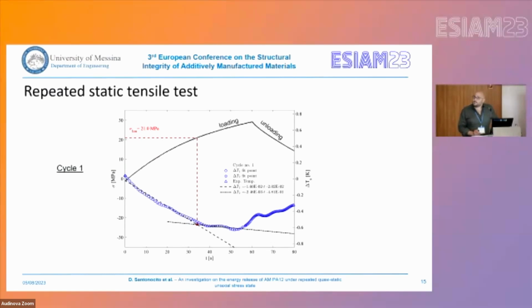Moving forward, we perform a series of repeated quasi-static tensile tests. Here I report the first cycle, where we have the loading curve that is stopped and then the specimen is unloaded till 0. Here we can see also the first linear phase and the second decrement phase of the temperature, and we can assess the limit stress as 21 megapascal.